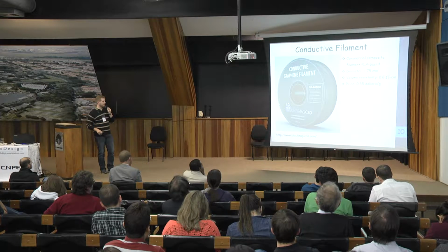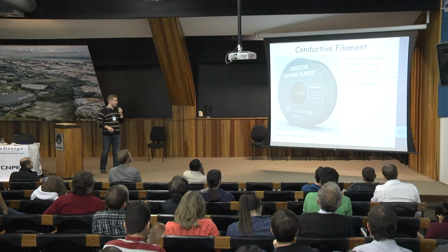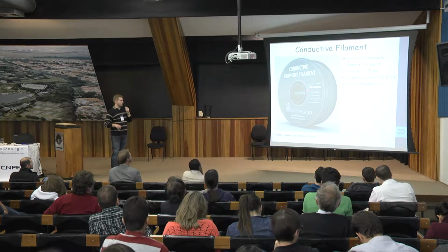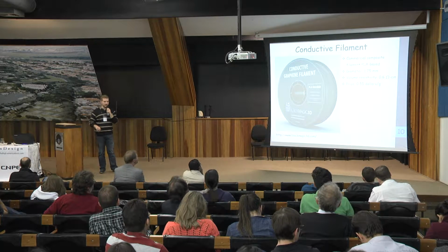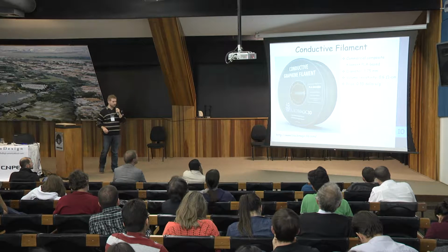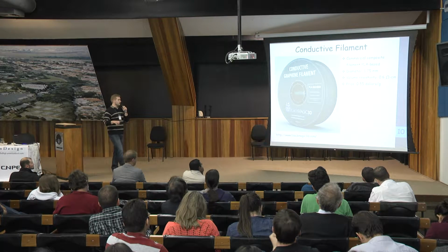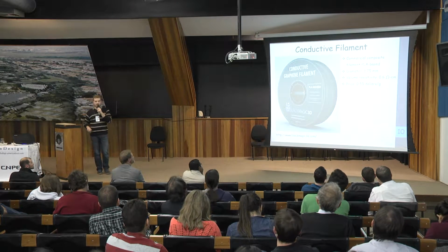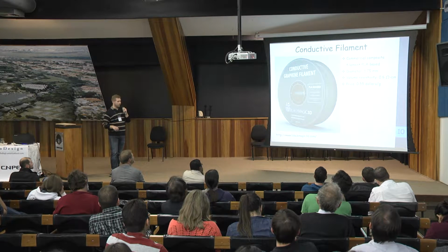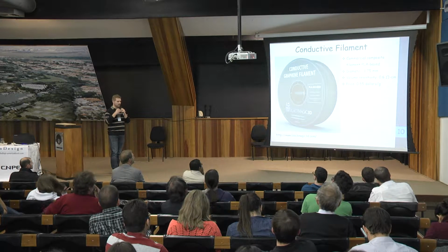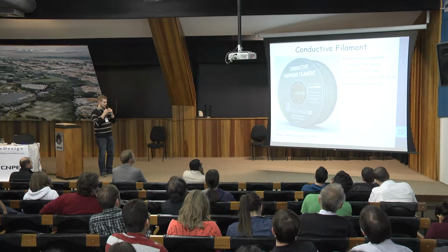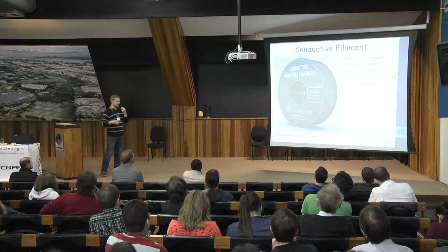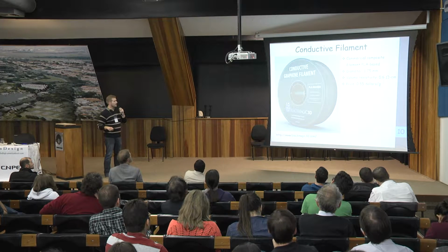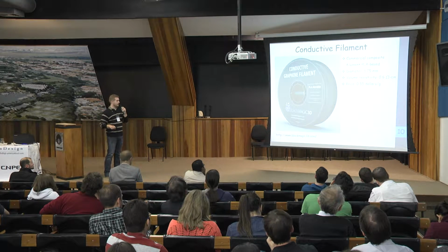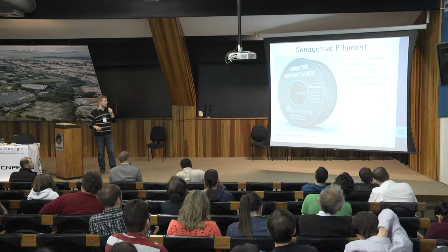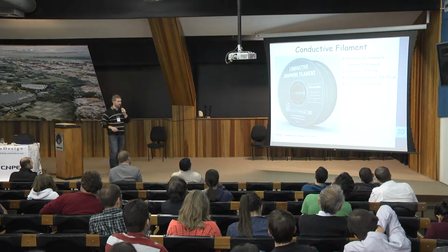And we found this conductive filament at Blackmagic 3D. It is a polylactic acid-based filament doped with graphene. It's based on the same thermoplastic, so we don't have problems printing, in adherence of one layer to another. It has a volume resistivity of 0.6 ohm centimeter, and it is a relatively cheap material.